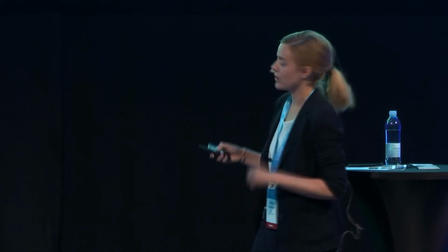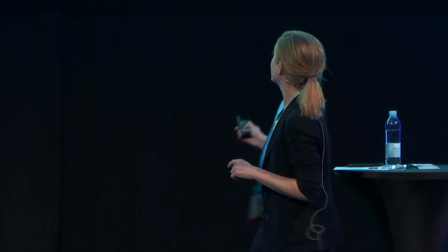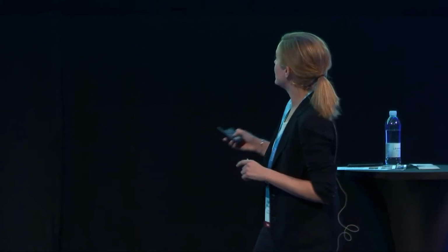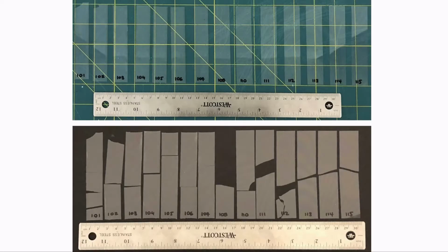Those three were sanded on the edge to see if improving the edge condition would enhance the capacity of those samples. And then we had two that we produced with the actual diamond wheel that we ended up purchasing for around $500, just to cut those things manually by ourselves, handmade.